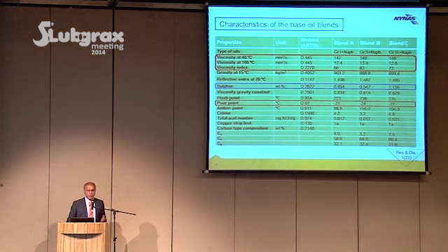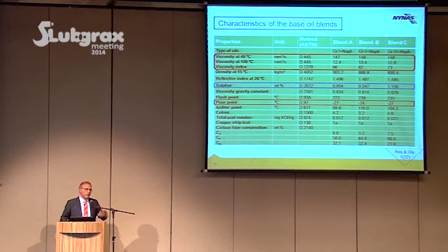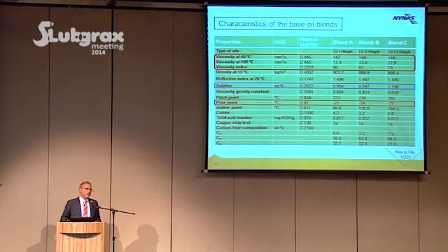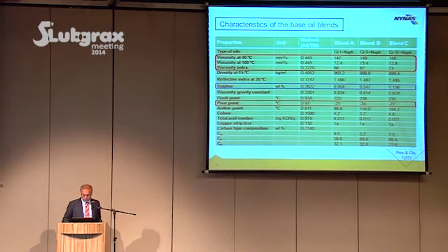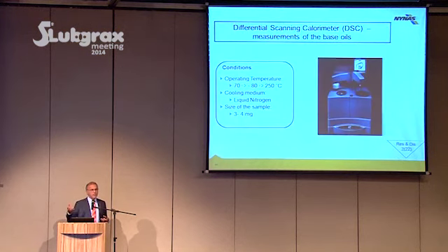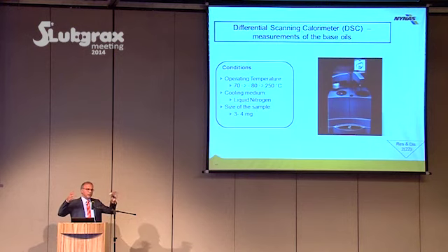The pour point of the paraffinic oil was about -12, -10, -12. After the blending, we ended up at -24 plus or minus 3 degrees C, which is very good. And when it comes to wax crystallization, as I mentioned, and pour point, there is a very clear relationship